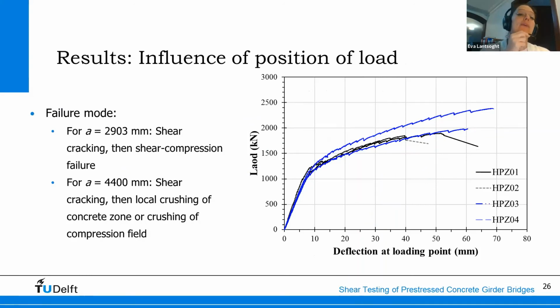Now, if we compare our results, we can see the failure mode changes as we change the position of the load. In all cases, we first had shear cracking and then could further develop the strength. But for loads closer to the support with a = 2,903 millimeters, we had clear shear compression failures, whereas for larger a, at 4,400 millimeters, we had either local crushing in the concrete compression zone or crushing of the concrete compressive field.